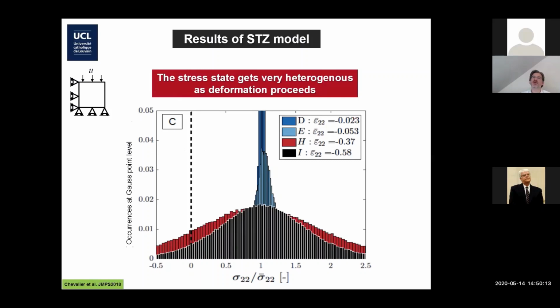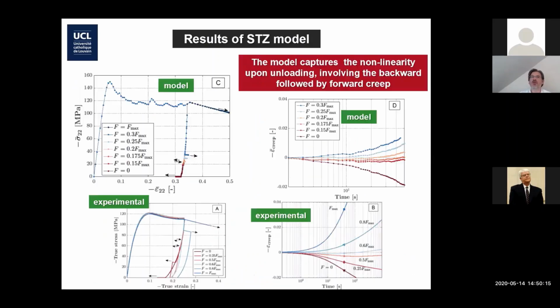Just the fact that when you unload, even under loading, you're already getting regions that are undergoing tension. So as soon as you're unloading, these regions are getting more and more in tension. They get to a point where they reach the peak stress in tension, and they start activating plasticity in the reverse direction. And of course, when this mechanism has been exhausted, then your stress is still positive. So you get the forward loading.